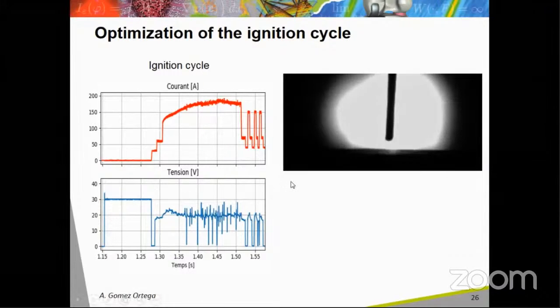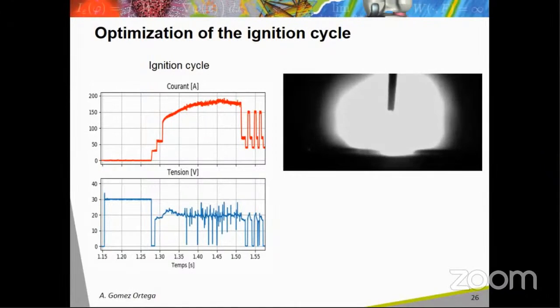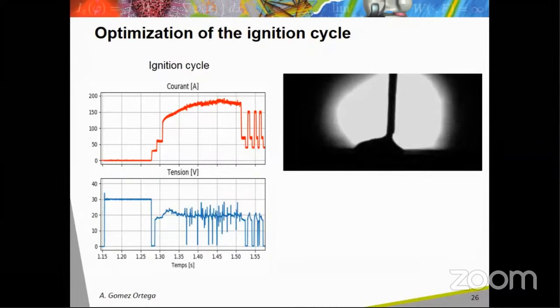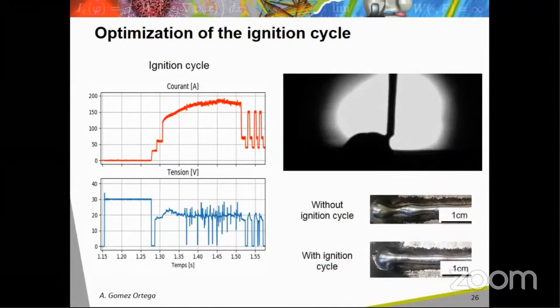One can see on the video the melting and spray of these small droplets that create a very hot melt pool with a better wetting of the substrate before the first short circuit at the beginning of the CMT cycle. So the optimization of the ignition cycle allows to reduce drastically the geometrical defect observed at the beginning of the deposit in aluminum alloy, as shown on this photo.